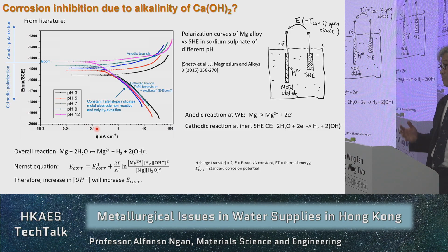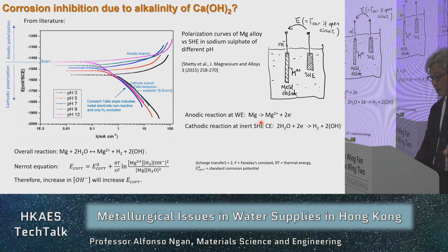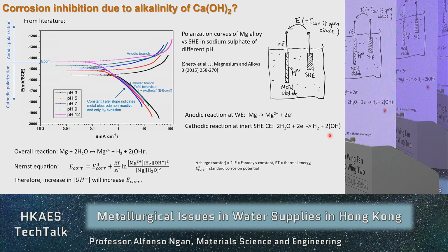corrosion curve for a typical metal, let's say magnesium, right? So in the magnesium, again, there will be an anodic reaction, which is like this. The magnesium will oxidize into magnesium ions. And there will also be a cathodic reaction, where just like what I've shown before for the steel, the water will change into hydroxide. Therefore, if you add these two, the overall reaction will be this. So if you add more lime, add more OH, you basically will drive the equilibrium of this reaction towards the left, and that is you would slow down the reaction.